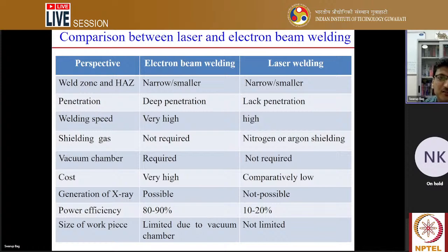But the cost is very high in case of the electron beam welding unit as compared to the laser. Generation of X-rays is possible in the electron beam welding process, but that is not possible in case of the laser welding process. But power efficiency for electron beam is very high, 80 to 90%, because electron beam welding occurs under vacuum, so we can expect almost all utilization of the power. But in laser welding, because of reflection of the light and other issues, the power efficiency is very low. Even power efficiency is very low in the laser welding process as compared to the arc welding process also.